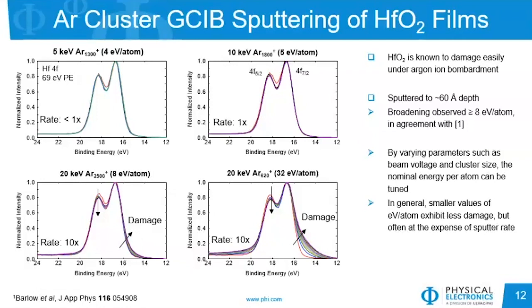In general, lower energy per atom does give us better performance as far as chemical damage related to the spectra, but we often find that that also is seen with a reduced sputtering rate. So there may be some trade-offs of how much damage is okay versus the rate that we want to sputter through for the throughput we need for our analysis.